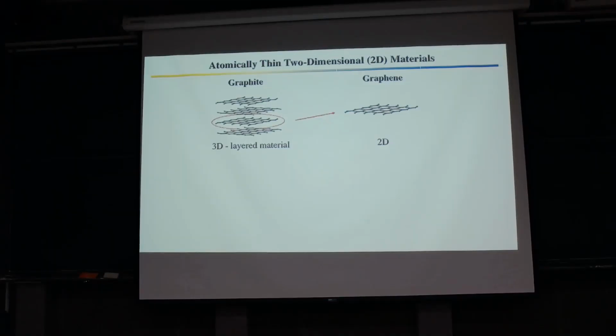Graphite is a layered material. Each layer is made out of carbon atoms in a 2D honeycomb structure. And the layers are very weakly interacting with each other. So you take one of these layers, then you'll have graphene. And because of the symmetry of the honeycomb structure, the low energy electronic states in graphene, in fact, have a very unusual energy versus momentum relation. It behaves like a massless Dirac fermion in 2 dimensions, and that leads to many fascinating properties related to graphene. Of course, graphene is not the only layered material in nature.